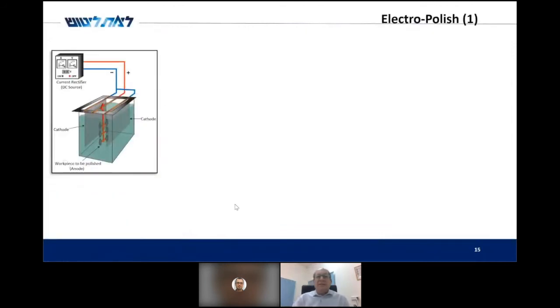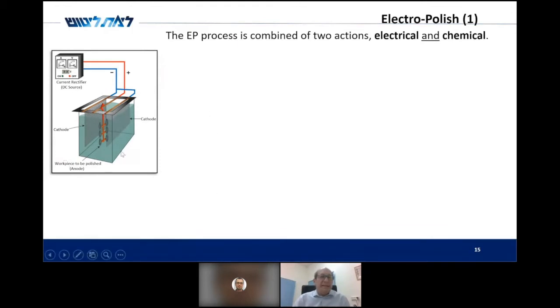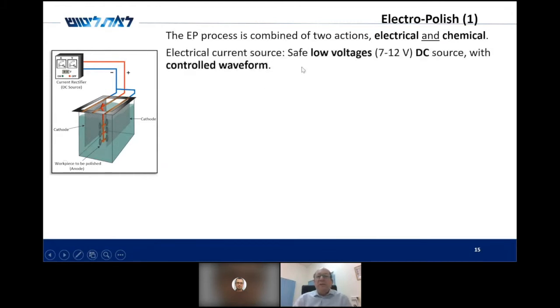Electro-Polish is a different process. It's a combination of electrical and chemical process. We can see here a bath with an electrolyte. There are two cathodes put in here, and the workpiece to be polished is connected to the anode, the positive pole. Usually we use quite safe low voltages between 7 to 12 volts from a DC source with a controlled waveform. Usually it's a step waveform. In some cases it is a ramp waveform. I will not go into these details.